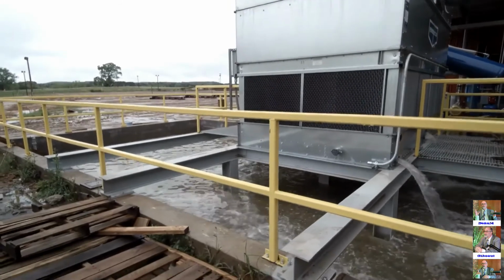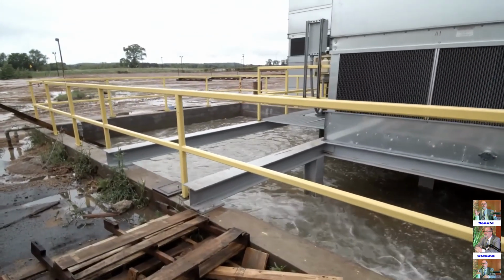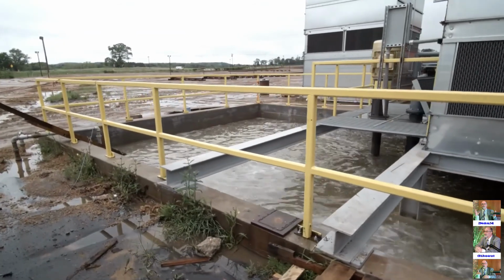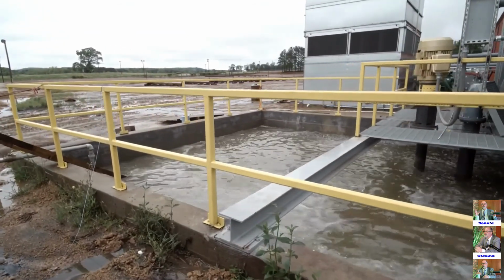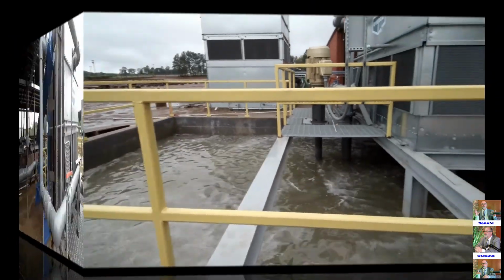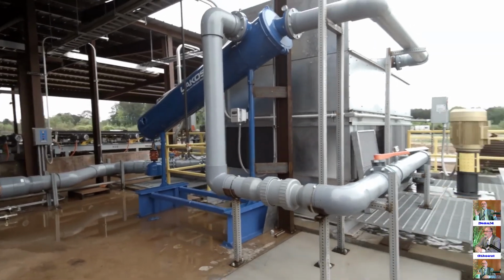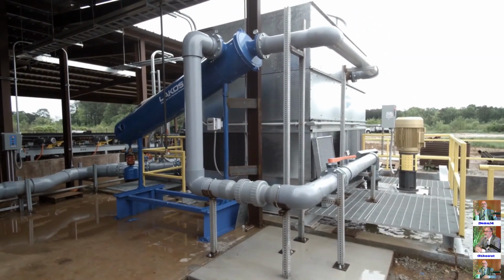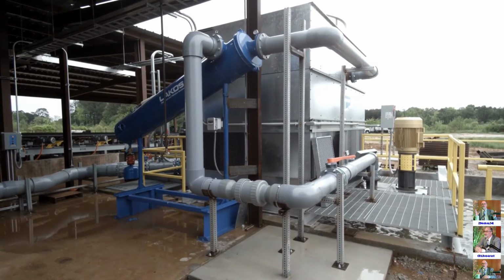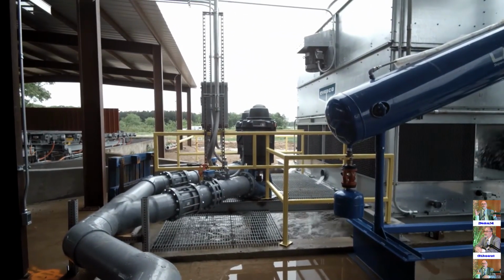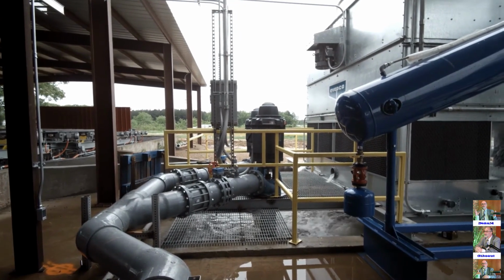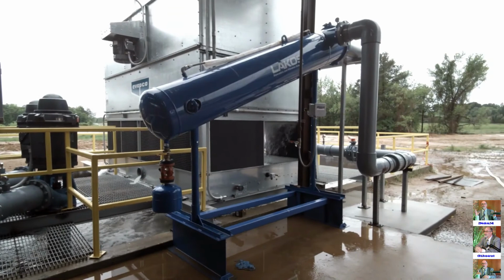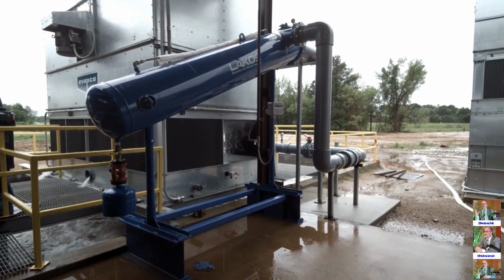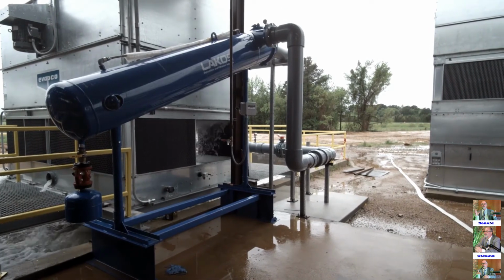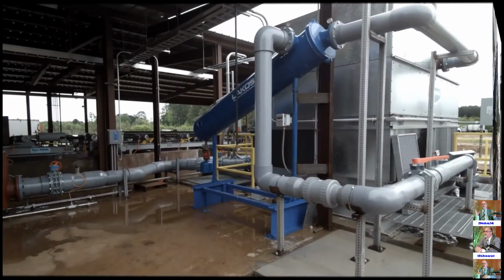But here's a common pit. We have an evaporative tower to cool the quench water down. There's typically an element heater in here just to maintain this quench. You try to maintain it in the high 90s Fahrenheit. This is a centrifugal separator. The quench water comes into a scale section, and then it drops over to what we call the hot well. And the hot well has a vertical pump that then pumps the quench water through that LAKOS centrifugal separator. Here's a back flush at the back of it here that goes in just a regular tote bin. But it drops back through the top of that tower after it goes through this centrifugal separator.